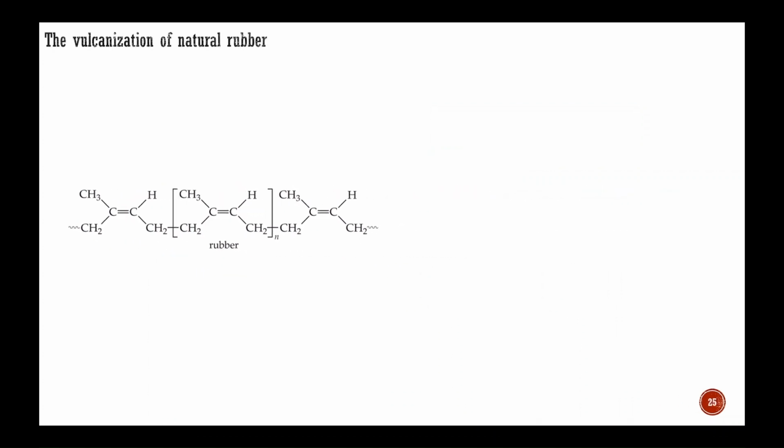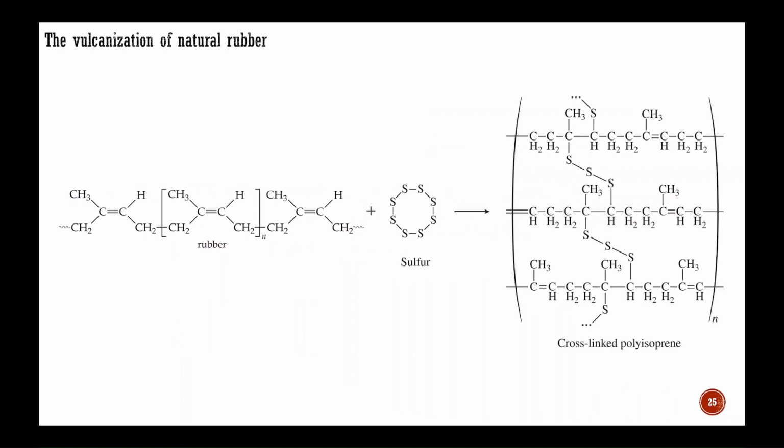During vulcanization, a controlled number of sulfur crosslinks are introduced by reacting the remaining carbon-carbon double bonds of adjacent chains with elemental sulfur in the presence of an accelerator and an activator compound. Vulcanization hardens the rubber and reduces its susceptibility to oxidation and other chemical transformations typical of olefins. Cross-linking approximately 5% of the double bonds creates a flexible, resilient rubber. When the rubber is stretched, the cross-links help prevent the polymer chains from slipping, allowing the material to retain its